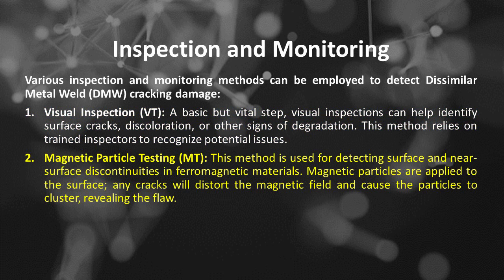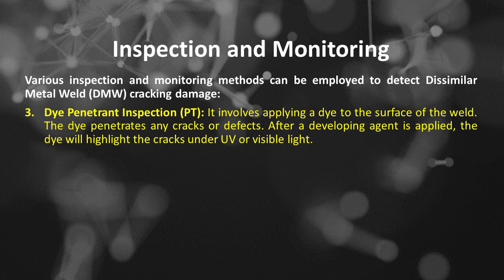Number 2 is magnetic particle testing, or MT. This method is used for detecting surface and near-surface discontinuities in ferromagnetic materials. Magnetic particles are applied to the surface, any cracks will distort the magnetic field and cause the particles to cluster, revealing the flaw.